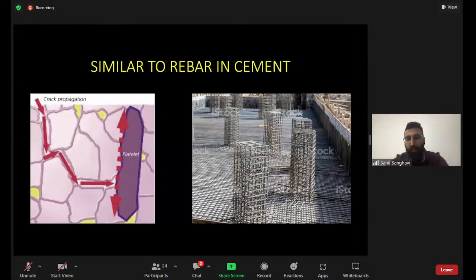So what is the main advantage of the fourth generation of ceramics? By adding strontium oxide and chromium oxide, you can see here that it forms a platelet kind of a plug in the microstructure of the ceramic. And this prevents the propagation of a crack. And this concept is similar to rebar in cement. For example, you might have seen on construction sites, you have these stainless steel wires or rebars which add additional support to cement columns, which is similar to what we do in THR. When we have large defects, we add screws and then pack it with cement. So the screws in that case act as a rebar, which is essentially what the elements of strontium and chromium are doing in 4th generation ceramics.